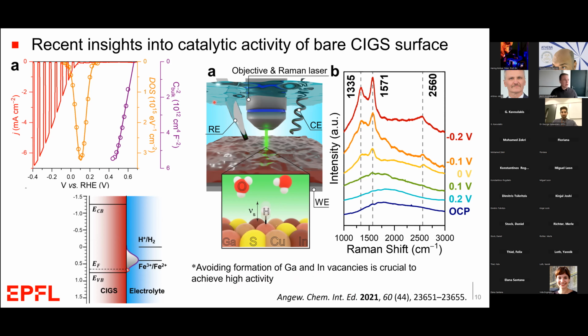So work goes on to try to understand if we can't achieve higher performance with these bare CIGS films and use them eventually in these photocatalyst type systems. But the drawback here, of course, is the very high overpotential that we need. You can see here our short circuit current at 0 volts is only about 1 milliamp, and we need to apply a higher potential to get all of the carriers out. So more surface engineering will be needed to make these types of materials useful for high efficiency hydrogen production.